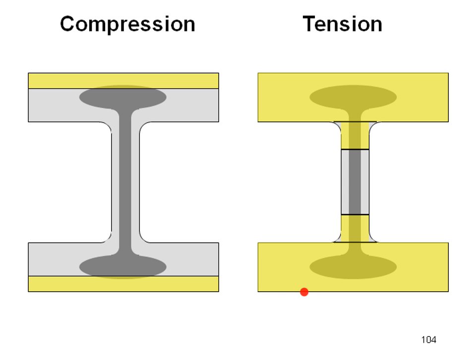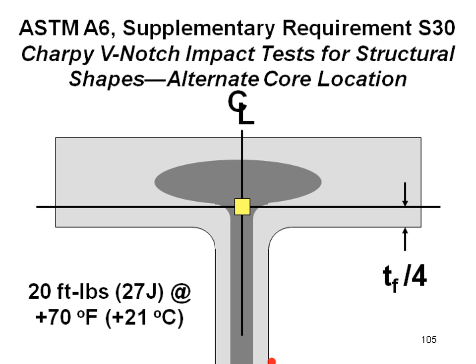Well, one of the things AISC imposed, and this is in the mid-'80s, these requirements started to come out, is now knowing about this low toughness core region, knowing that the ASTM location was on the tips of the flanges, AISC imposed a new requirement for these jumbo sections, and that was that the CVN specimen would be taken out of this worst case location, the center line of the shape, and T/4 into the flange.